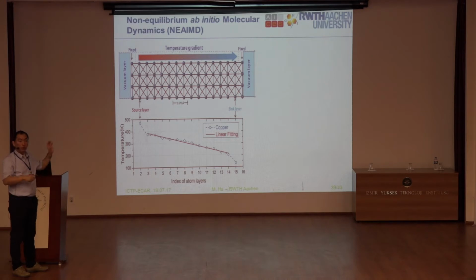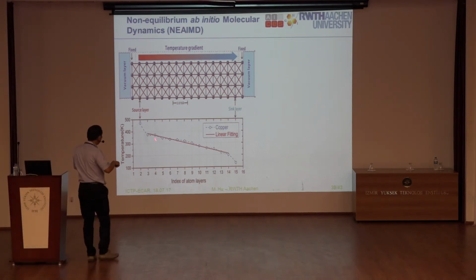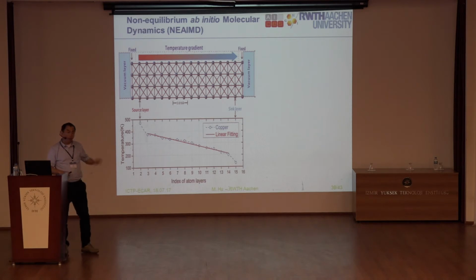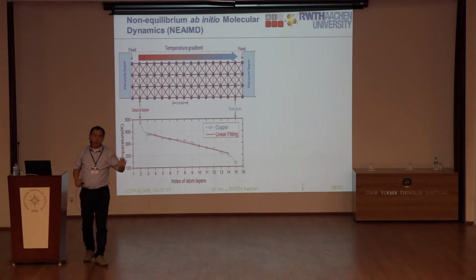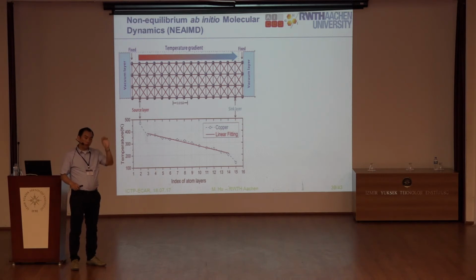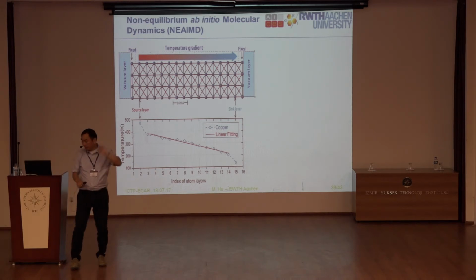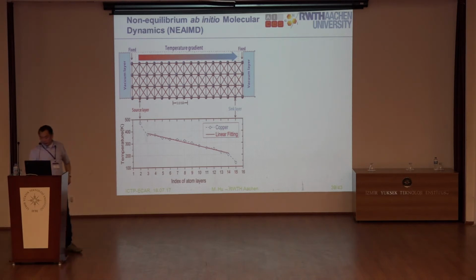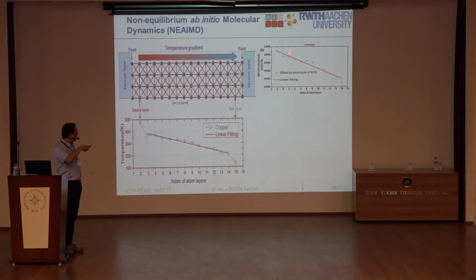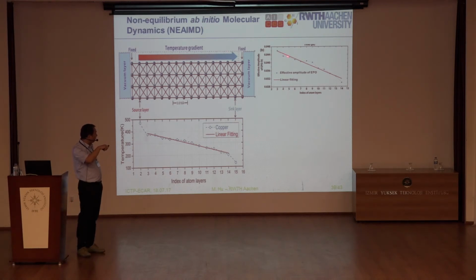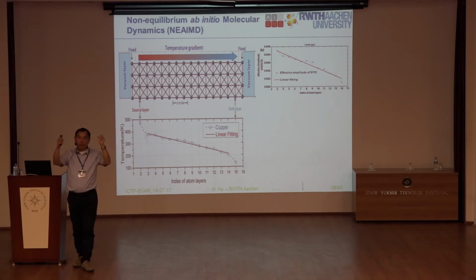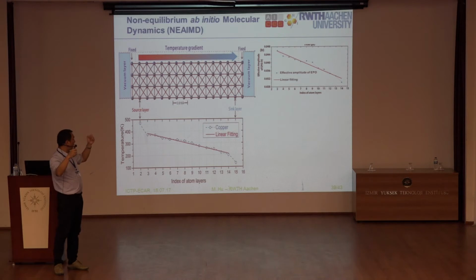That's easy, right? Of course, right now we are doing the non-equilibrium ab initio molecular dynamics to the pure metals, not the semiconductor anymore. So now we have the temperature gradient. Okay, that's easy to understand, but we have to realize that this temperature means the vibrational velocity of the nuclei, so metal ions. And then with this temperature gradient, in the meantime, you also establish another gradient for the electrostatic potential oscillation. So you have in the space, if you have a temperature gradient in the metals, you also have the electropotential gradient in the space.